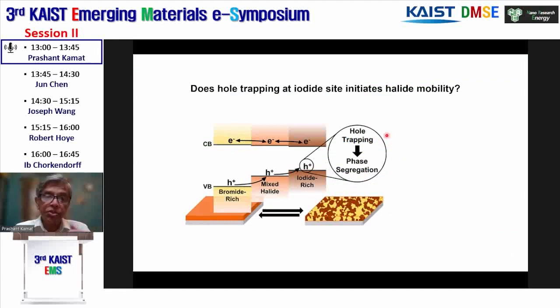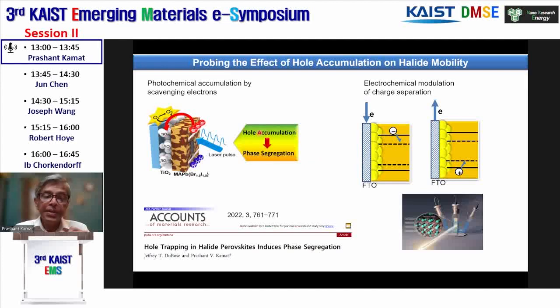So with that in mind, what I've been telling you is, when you shine the light, essentially these holes accumulate at the iodide-rich phase. And this is what we consider as the driving force for making this iodide. So in the next few slides, I will show you how we prove this hole accumulation is leading to this iodide migration. For example, we did two separate experiments, different from the steady state photolysis. One is a laser pulse excitation.